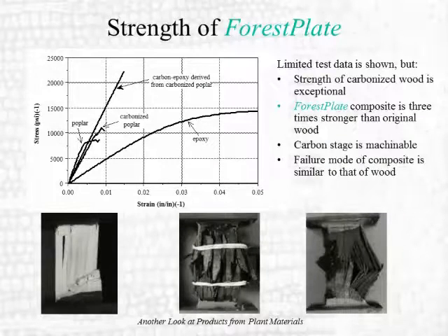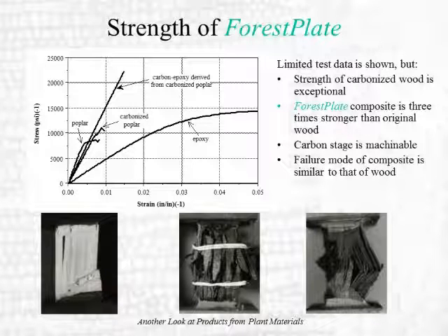So full densification is possible using the right approach. You get a material that you can shape using conventional tools. You can polish it to give it a high luster. It has all the grain features, and it is dark like ebony wood. It has strength. This is a compressive strength. Surprisingly enough, the wood charcoal in compression with the grain was stronger than the precursor wood. When you infiltrate it with the resin, you get twice or more of the strength in compression against the grain.